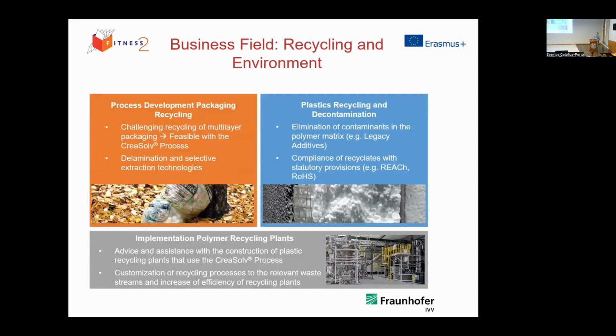Our department is separated into 3 different working groups. One is focusing on the recycling of packaging materials, especially multi-layer packagings, which is currently very challenging. And for that, we have delamination processes, but also selective extraction technologies. Another group is focusing on the decontamination of plastic wastes to eliminate the contaminants in the polymer matrix, for example, legacy additives, to obtain recyclate in the end, which is in compliance with statutory provisions. And if we want to upscale such a process, we have another working group for that, they give advice and assistance in the construction of recycling plants that use the CreaSolv process, and they also customize each recycling process to the specific waste stream to increase the efficiency.